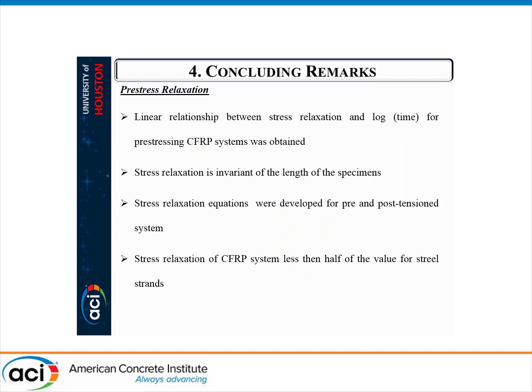So the concluding remarks are the linear relationship between stress relaxation and the logarithm of the time. Stress relaxation is invariant of the length of the specimen, and the equations were developed for both pre-tension and post-tension application. And relaxation of CFRP systems is less than half of the value for steel.